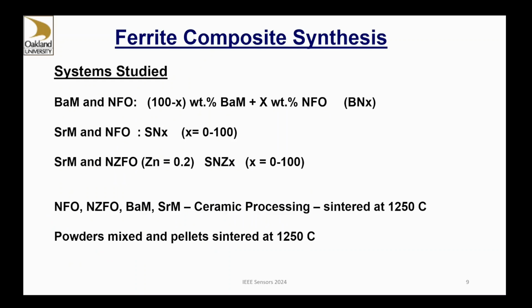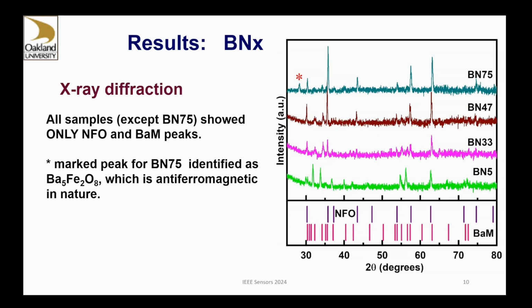So we made composites with a series of weight percent of the hexaferrite and the spinel ferrite. For example, this particular composition, we call it BNX. X represents the weight percentage for the nickel ferrite. In a similar way, NZ is nickel zinc ferrite. X is once again the weight percent of the spinel ferrite. And as I just mentioned, we made these by ceramic processing, and after that, the powders are mixed in proper proportion and sintered at 1250.